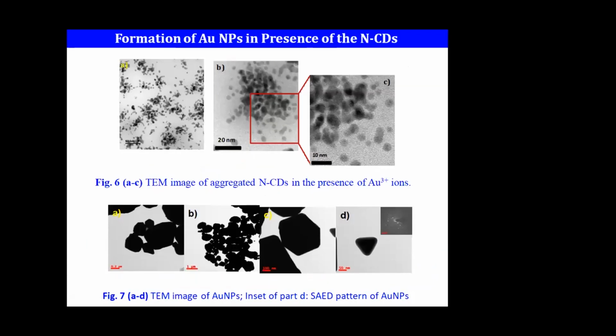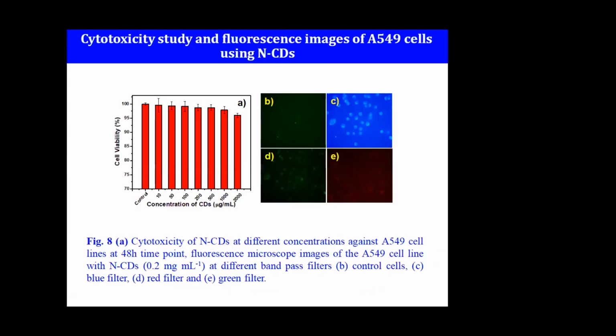Again, surface characterization using TEM imaging shows that as you add gold to this, there is aggregation of the CDs happening, which we could picturize better in the TEM images. Different kinds of aggregation shapes were found happening for the carbon dots.